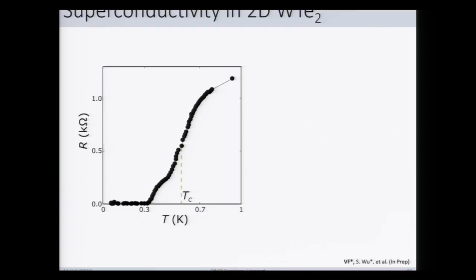So here's the resistance as a function of temperature for a selected gate voltage. And it drops, again, starting from around 1 Kelvin and reaches 0 at a little bit above 300 millikelvin in this case. And a little bit later, I'll be designating TC just for convenience at about the halfway point compared to the normal state resistance.